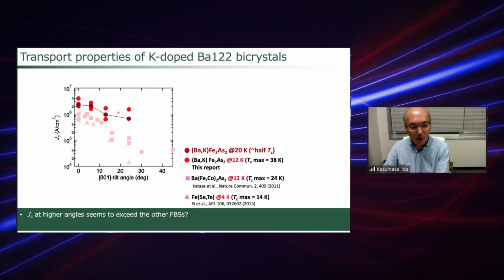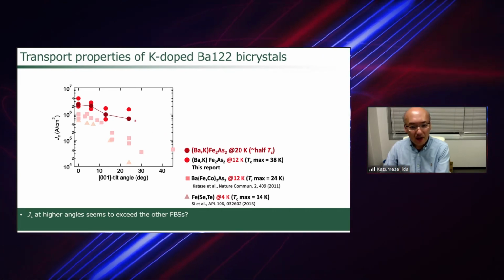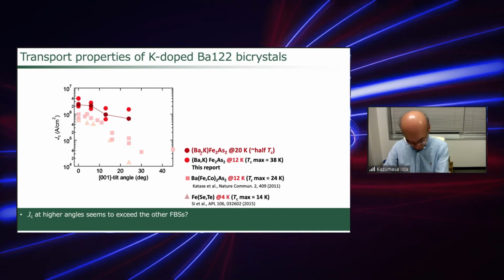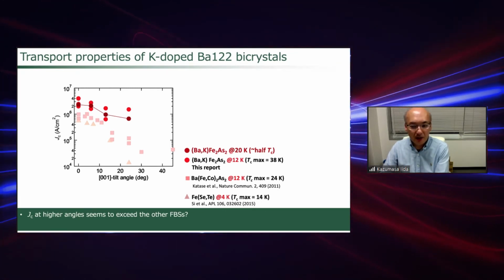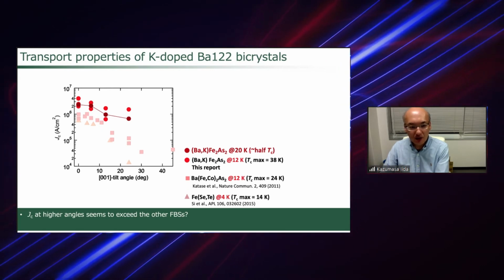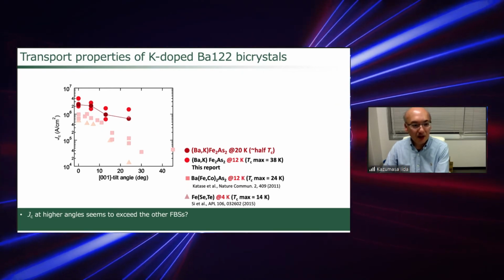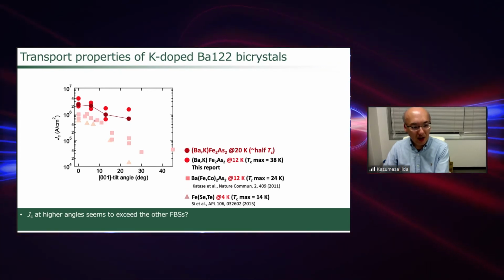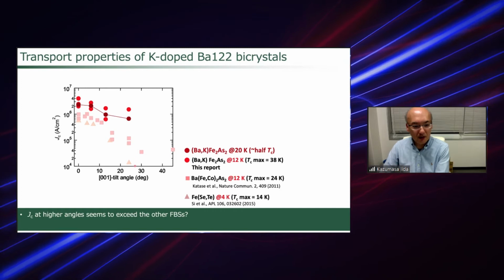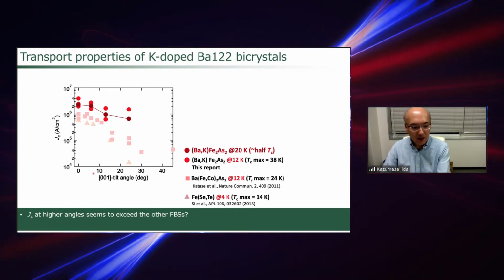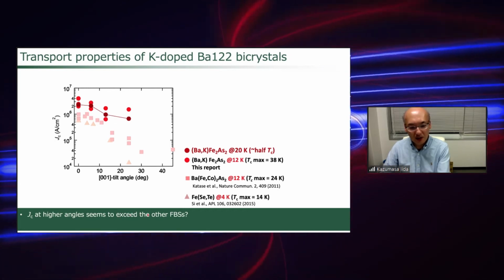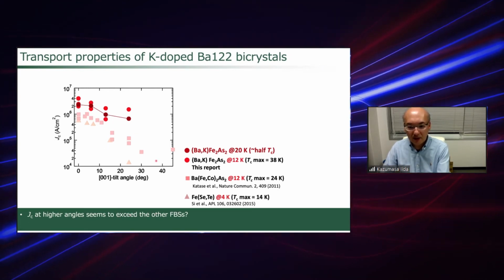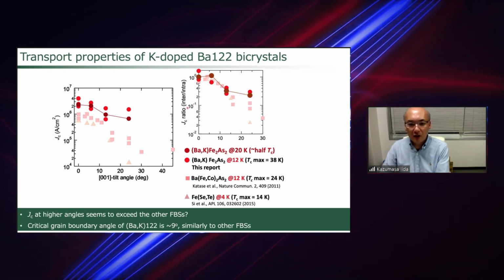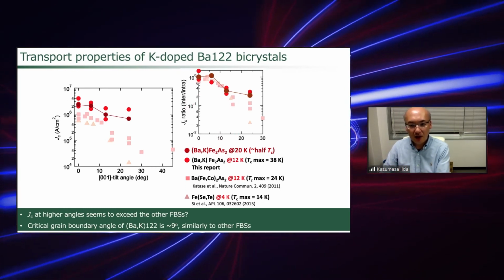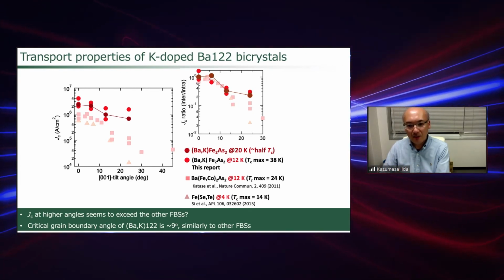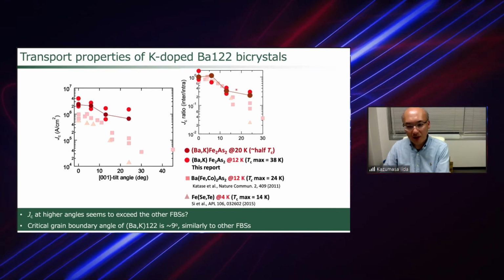Of course, this is not a fair comparison because the Tc is high, and therefore we measure the intergrain Jc at 20 Kelvin, which is half of the Tc of 38 Kelvin. But even at half of the Tc, the intergrain Jc is much higher than the cobalt barium 122 and also the iron selenide telluride, which means that the Jc at a higher angle seems to exceed that of the other iron-based superconductors. And we plot the normalized Jc as a function of the misorientation angle. But in this case, the trend is almost the same as the other iron-based superconductors.